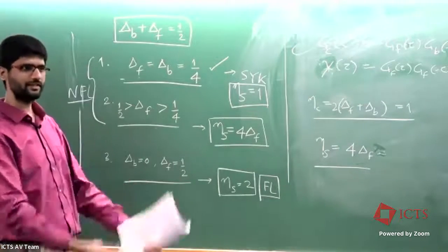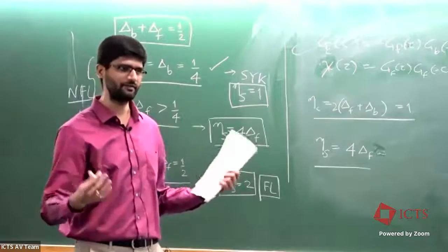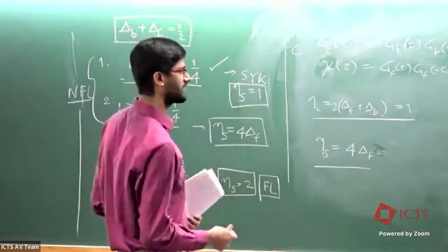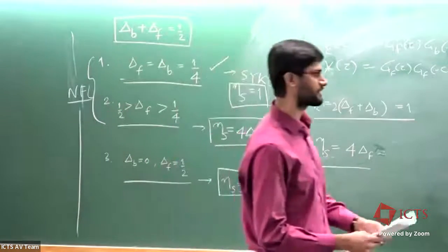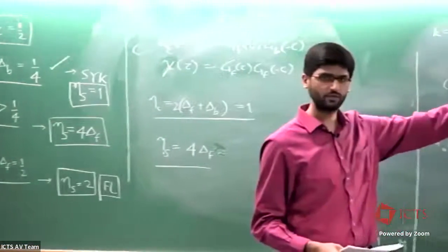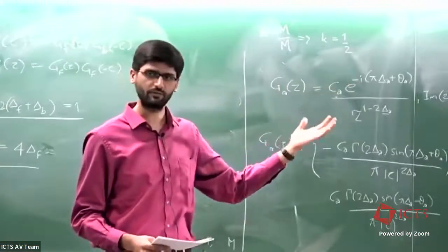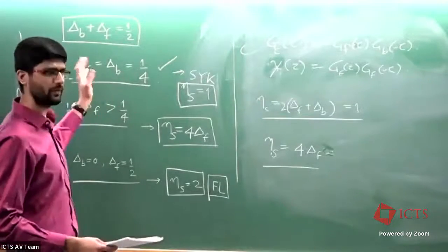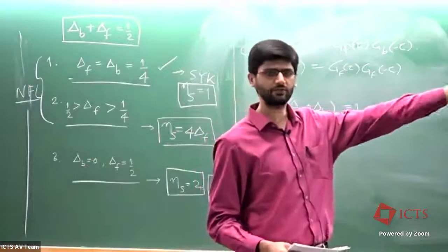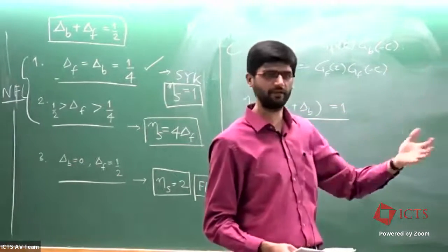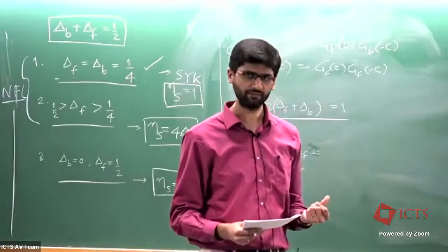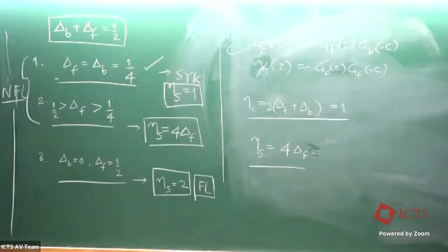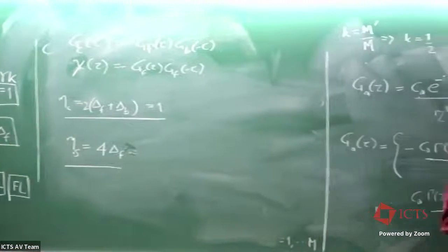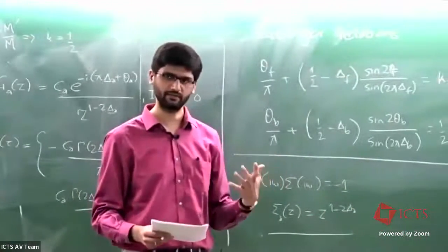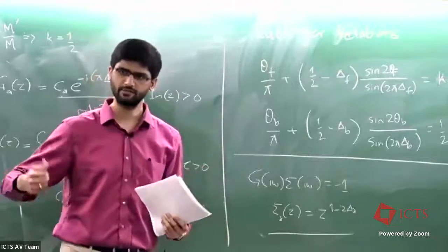Now we actually have to go and see which solution appears at what value of doping. So that's the task. And this task is aided by the Luttinger relations, because those relate your doping to the actual parameters of the ansatz that you have introduced in your problem. So now, guided by the solution, you can ask the question: suppose I choose solution 1, you know what the value of delta is, you put it back there, and then you solve for a given doping the values of theta_F and theta_B, and see where the solution is stable. It turns out that this 1/4 solution, the SYK-like solution, is confined to a pretty small doping region. It appears at smaller dopings, and doesn't appear at very large values of doping.